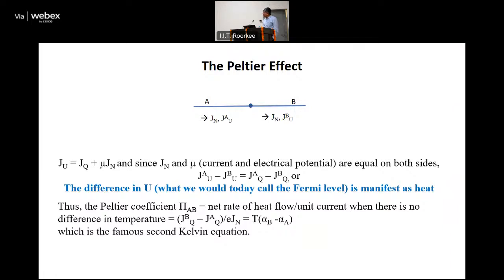So the Peltier coefficient is then written in terms of the temperature and the Seebeck coefficient, which is the famous second Kelvin equation. So, in a sense, all we've done is re-derive everything. But the assumption that Kelvin made, that you would apply the first law, the laws of thermodynamics, to a transport process, has been put on a firm mathematical foundation by this process of relating how the system responds to a small change by equating that to the way in which, at equilibrium, it deals with fluctuations.